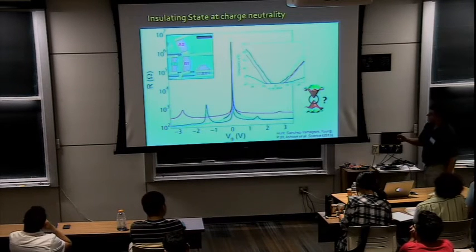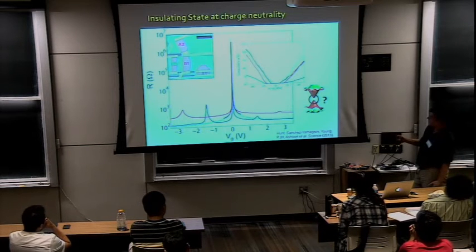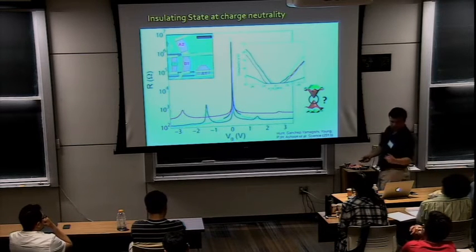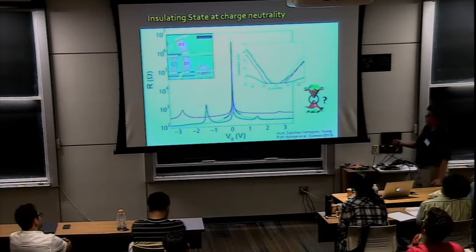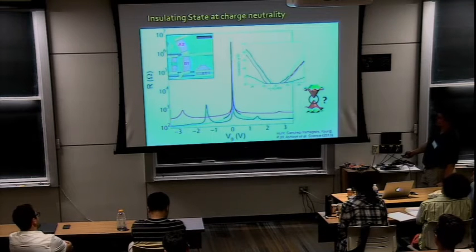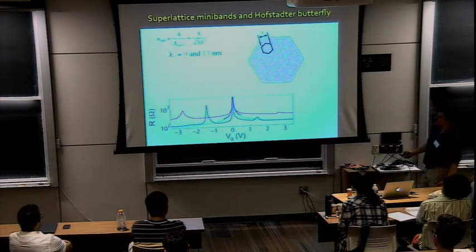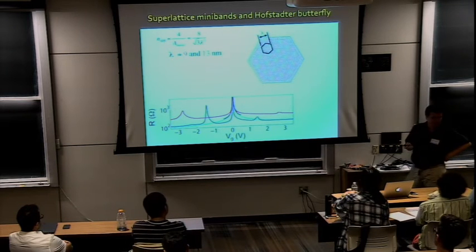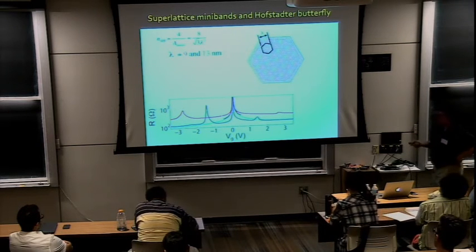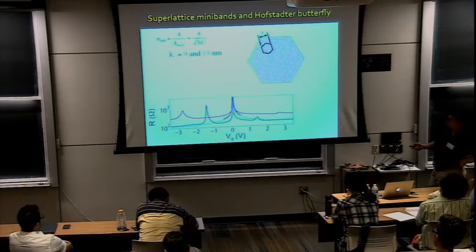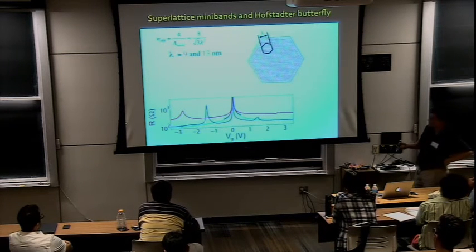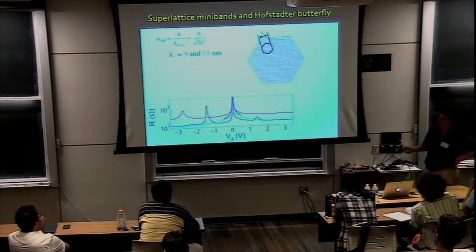So this made us wonder, okay, it seems like we're actually opening a band gap in graphene. Okay. Now, before I continue the story about the band gap, let me tell you about an accidental nice thing that happened at the same time. It turns out that these Moiré wavelengths for graphene on hexagonal boron nitride, for this red and these blue curves devices here, are 9 and 13 nanometers. Okay? We can calculate that from the density at which these peaks occur.